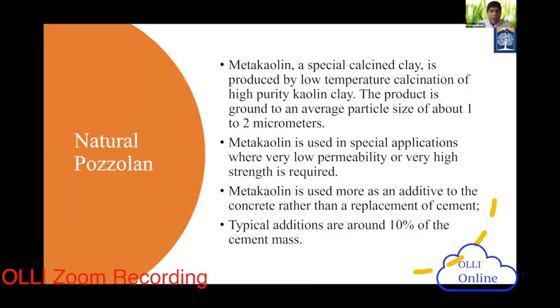One of the materials that we have used in our lab is called metakaolin. It's a special calcined clay, produced by low temperature calcination of high purity kaolin clay. Probably you have heard about kaolin clay. That product is ground to an average particle size of 1 to 2 micrometer. You can imagine how fine that material is. It is similar to silica fume, like 50 times finer than your original Portland cement. So same effect: binding better, voids are reduced, impermeable concrete.